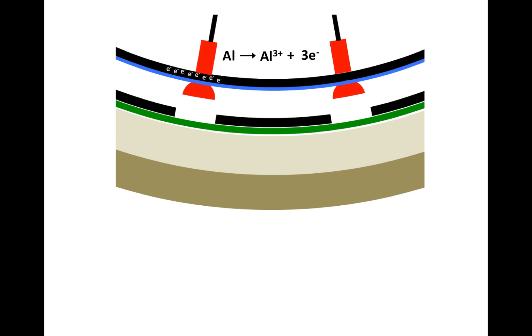As the aluminum is oxidized, the electrons in enormous numbers flow into the rim. In this first portion of the corrosion reactions, aluminum is acting as the anode, and the carbon composite rim is acting as the cathode.